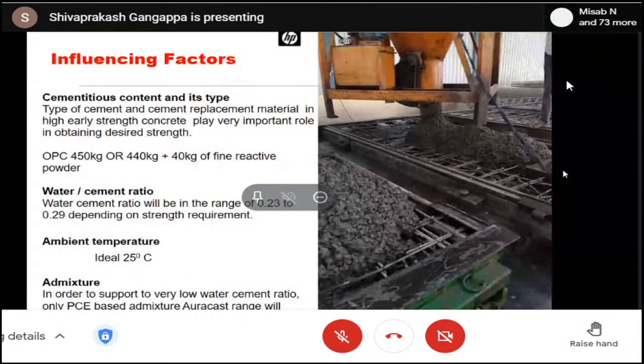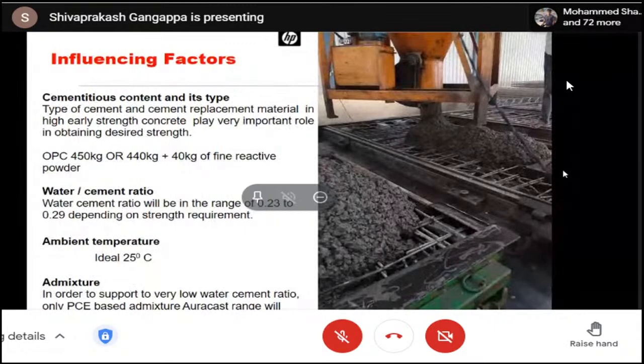The fine reactive powder can be microsilica, because if you really look into the ingredients or the fineness of microsilica. The microsilica's fineness is such that each particle of microsilica, if you spread it out and see the area, 1 kg of microsilica can give an area of 18,000 square meters. So this is a highly reactive powder, and the surface area is so huge.